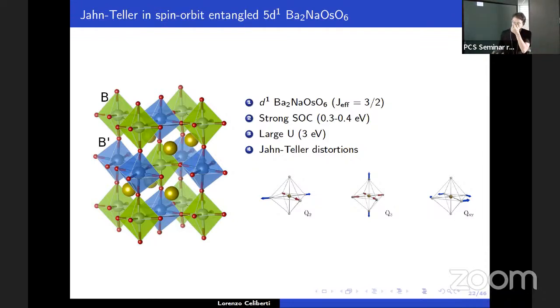It depends also on the reference structure with respect to your measures. With the Q1 mode, you're not lowering the symmetry of the local environment because the octahedron is perfect. Whereas with this other one, you have a lowering of the symmetry, which also splits the level. The sodium site is really independent, easy to move. So the breathing mode is somewhat easy. But what we will see later is that more important in our case is this tetragonal distortion and orthorhombic distortion. But maybe we can discuss this also later, because otherwise I don't know if I managed to explain.